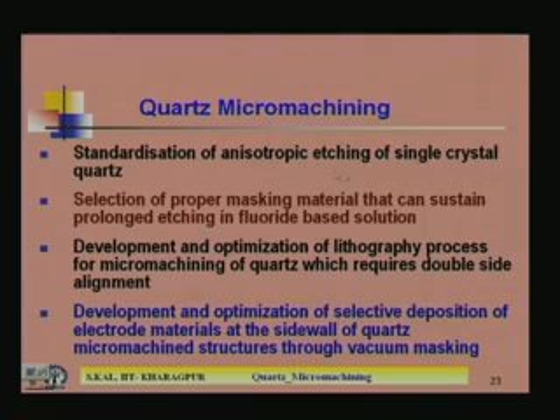Okay. So, these are the advantages, and if you go for quartz micromachining, then you have to go for certain steps. What are those? Standardization of anisotropic etching of single crystal quartz, you have to do. Selection of proper masking material that can sustain prolonged etching in fluoride based solution, because all etching solutions of quartz are fluoride based. So, there you have to select a mask which can withstand long exposure to the fluoride based solution. Third point is development and optimization of lithography process for micromachining of quartz, which requires double side alignment.